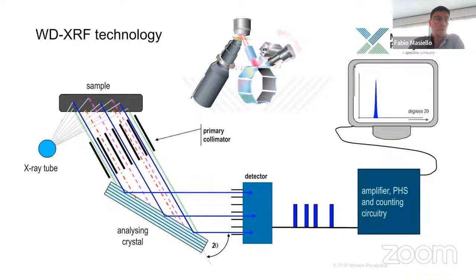As I mentioned, there are two different configurations for an X-ray fluorescence instrument. One is the so-called wavelength dispersive X-ray fluorescence technology, where you have an X-ray tube, which produces mostly the Bremsstrahlung curve, that will irradiate your sample. Like I mentioned before, some electrons are kicked out and other electrons will occupy the vacancy, therefore creating the so-called characteristic X-ray lines. Then by using an analyzing crystal and a counting detector, you can look at different energies by turning the analyzing crystal, and see which characteristic lines are inside my sample.